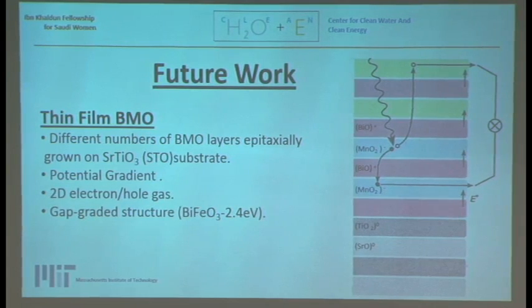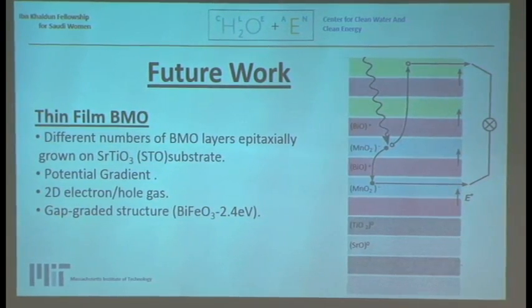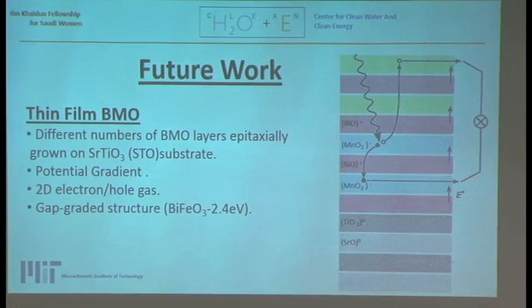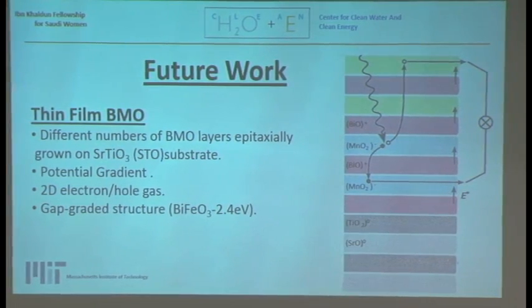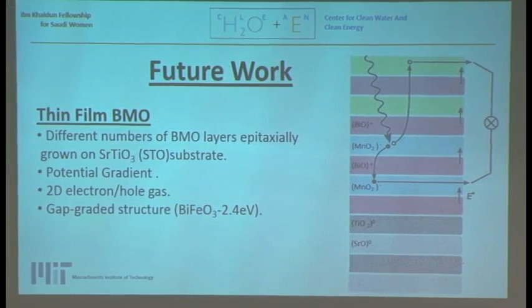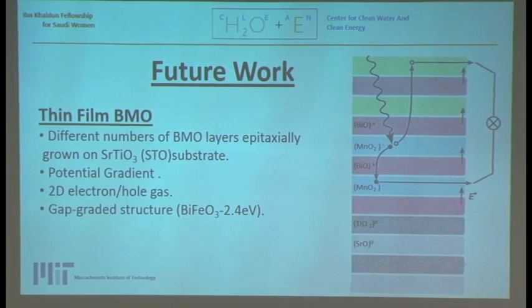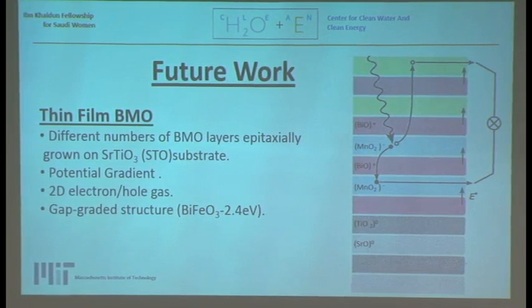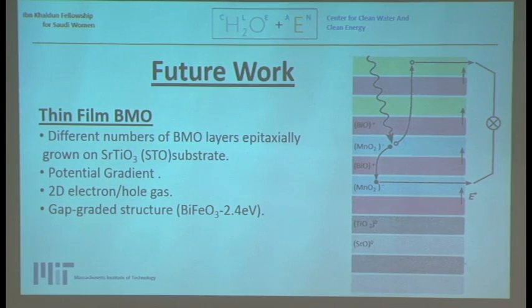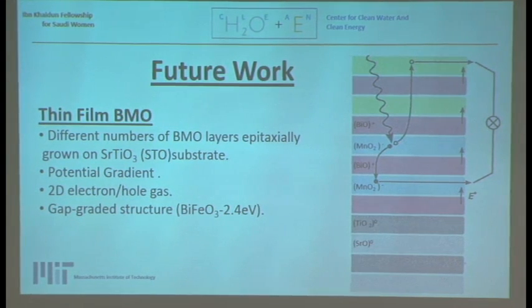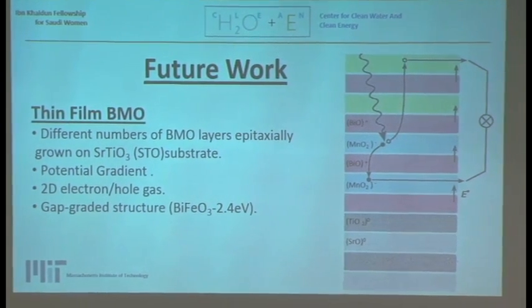And finally, the efficiency in the high energy region of the solar spectrum can be improved by introducing another transition metal oxide with a larger band gap, such that the layer or material facing the sun has a larger band gap than the material underneath.